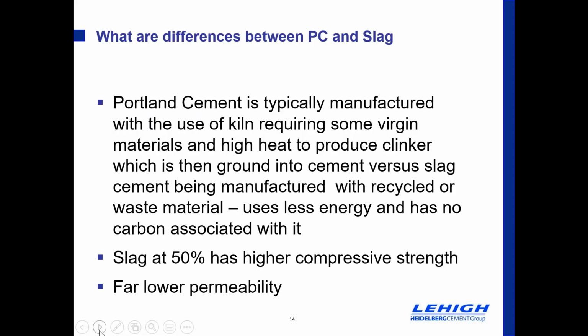So, what are the differences between Portland cement and slag? Well, as I said earlier, cement is typically manufactured with the use of a kiln, requiring high heat and some virgin materials to produce a clinker, which is then ground into hydraulic cement, versus slag starting out as a recycled waste material. What you saw in that molten form, we've now processed slightly more to turn it into glass, to turn it into a cement. That process uses less total energy and has no carbon associated. The carbon is associated with the making of the Fe, and this is looked at as a recycled material, driving some of its increased use around the world.